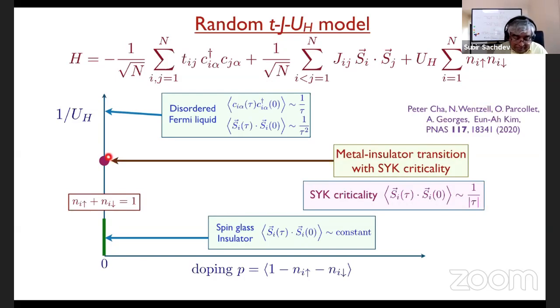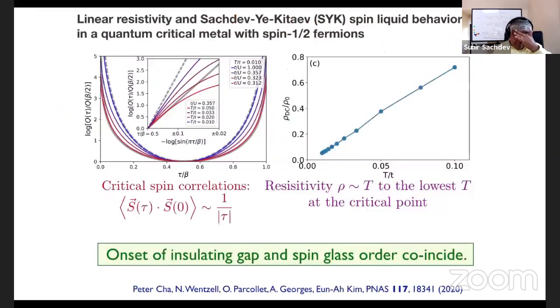But anyway, what they found was that there were only two phases: a spin glass phase and a disordered Fermi liquid, with a critical point in between them. And to me, this was really extremely exciting, and this is really part of the motivation for a lot of this work. This is before our work. They found that the spin correlations have this 1/tau decay that's so characteristic of SYK models. So here's the actual numerical evidence at the metal insulator transition. I won't go into details. They also found that the spin glass order appeared to extend all the way up to the metallic point, though they didn't have detailed results in the spin glass phase.